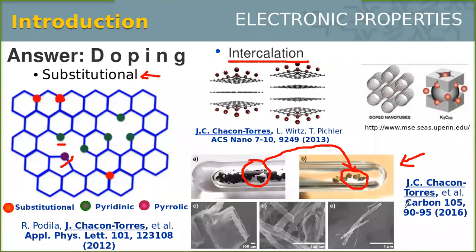This is something extremely interesting, because all these optical changes are derived from the intercalation of potassium, or alkali metals, metals that donate electrons into the carbon structure, so that the material gets an excess of electrons, and that moves the Fermi energy level into a place where we can access different bands from the electronic band structure of the material.